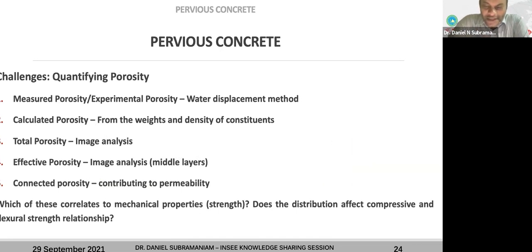Right. So after this, the quantification of porosity. I will be talking a lot about this later on. We are actually talking about five porosities here: the measured porosity, the calculated porosity, the total porosity, the effective porosity, and the connected porosity, which is going to contribute to the permeability.